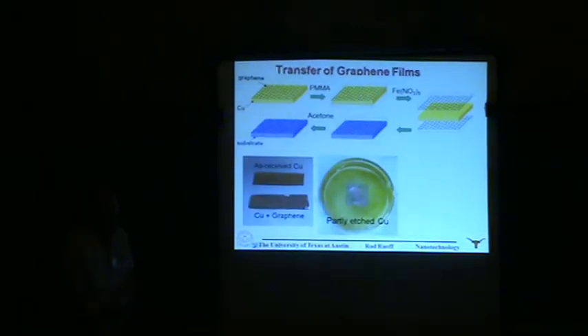So this led to the first example of growth of clean monolayer graphene over a large area. And it's had a very significant impact worldwide. And so we were sort of fortunate that the growth was a different mechanism than we were thinking it might be from thermodynamic binary phase diagrams.